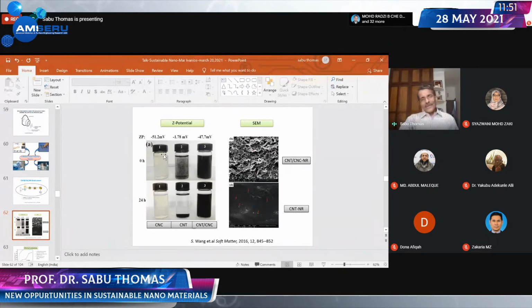This is a very simple experiment. In a small glass bottle, you take nanocellulose. Keep it for 24 hours. Very stable, no settling down of nanocellulose crystals. You do the same experiment with CNT. This is CNT in water. And you keep it for 24 hours. What happens? Very unstable. CNT settles down. But you take a 50-50 combination of CNT and nanocellulose together. Look, no settling down of CNT. You get fantastic dispersion.